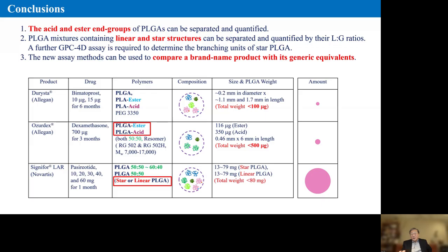First of all, I just want to emphasize here that when we hear PLGA star-shaped polymer, please understand that the branching number is not 4 or 5. It is usually almost always less than 3. So it's somewhere between 2 and 3. So PLGA branching number 2.5, for example, means that most of them are not branched PLGA. There are lots of linear PLGA too. So that is a reality. That's why, if you compare the raw materials after you make a final formulation, the composition will be very different.